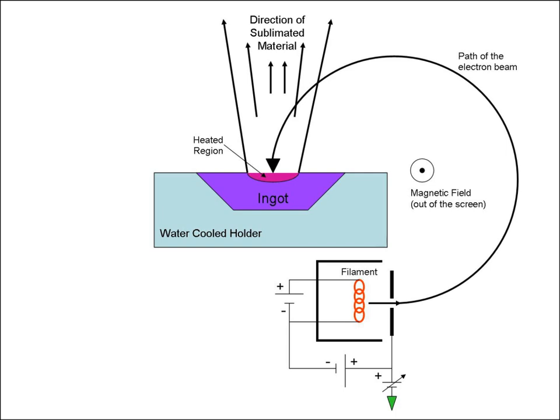In the reactive evaporation process, the metal is evaporated from the ingot by the electron beam. The vapors are carried by the reactive gas, which is oxygen in case of metal oxides or acetylene in case of metal carbides. When the thermodynamic conditions are met, the vapors react with the gas in the vicinity of the substrate to form films.